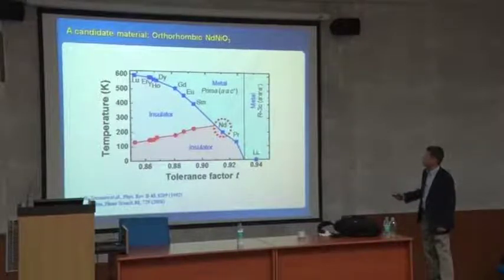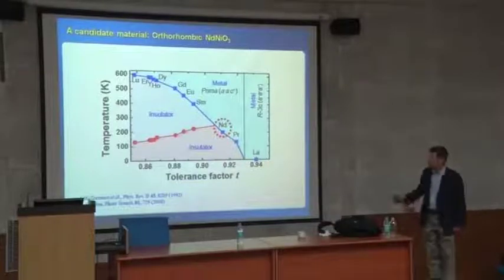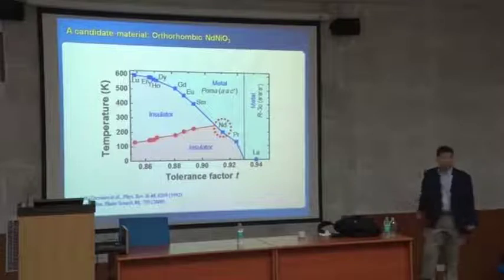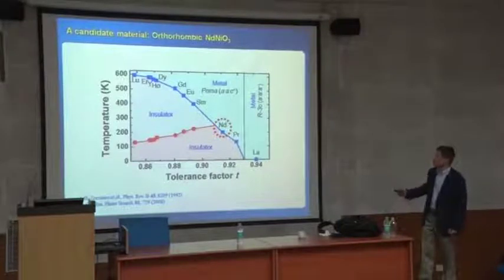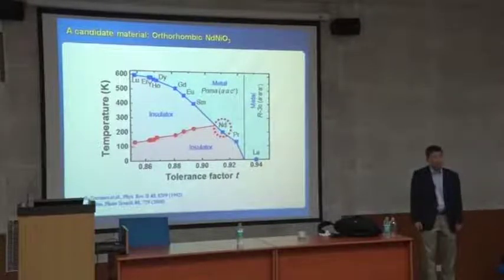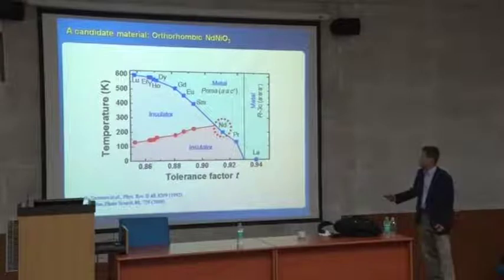Lanthanum is a metal, or neodymium is a metal, or praseodymium is a metal. Okay, at room temperature. Is the room temperature 300 Kelvin here? Right? And room temperature, this is a metallic region, and this insulating region is 300 Kelvin. You draw the line here, draw the line here. And samarium is a 300 Kelvin insulator. Everything insulator, right? So that's what all of those disqualified. And the only things qualified are these three.